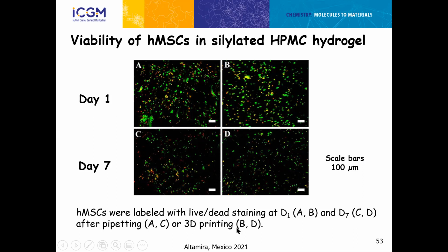With 3D printing, it's B&D, and by pipetting you print first and then you add your cells. Here you print your hydrogel containing cells already. So as you can see, there is no difference. After 7 days, the viability is around 60%.